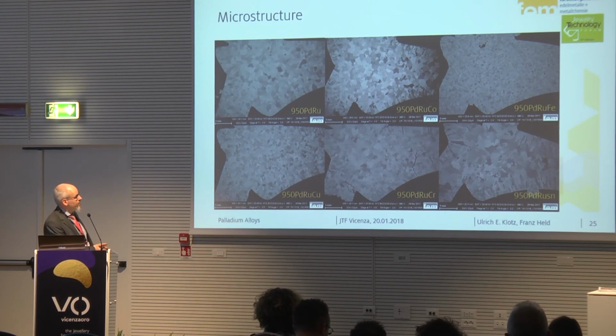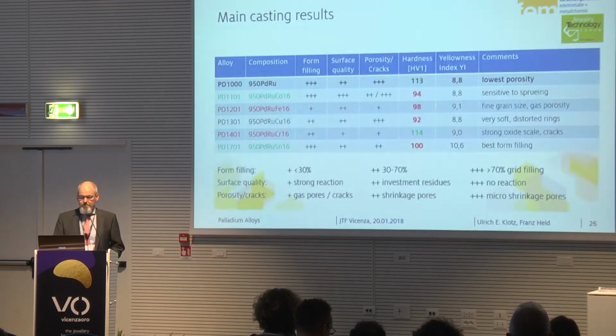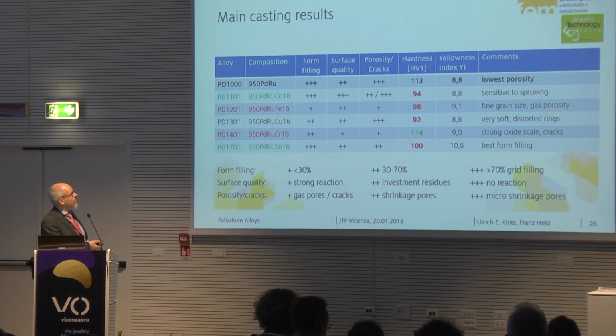Microstructure. This is a close-up view of the images you just saw, but here we see the grain size. So we see palladium ruthenium has a medium but relatively regular grain size. Elements like tin result in a coarsening and columnar grain size here at the edges, and additions like iron result in a very fine grain size, which is beneficial. Chromium results in cracks.